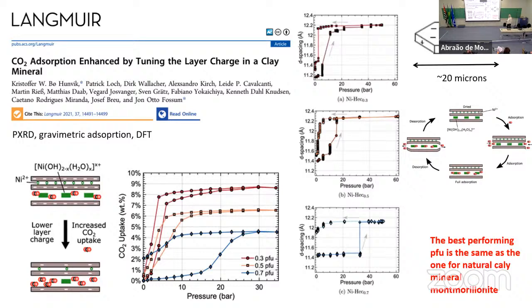We did some other work, which was to synthesize the clays in different ways so that we can play around with the surface charge on the clay platelets, in such a way that the surface charge controls the number of cations sitting there. So we found that lower surface charge, meaning lower number of interlayer cations, is more efficient for capturing CO2. And we believe that is due to the fact that when you have fewer cations, there is more space for CO2 to be captured. We have these nickel hydroxide islands in there, and there's more space around them and more edges, so we capture more CO2.